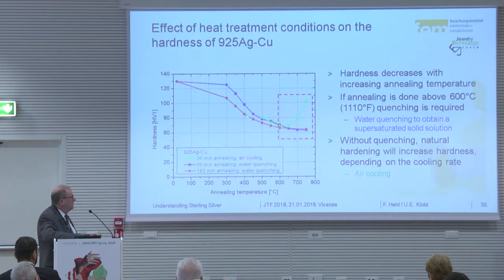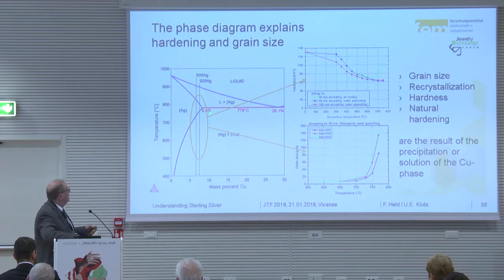If we make annealing and take it out of the oven and lay it somewhere, we see that the hardness increases again, and we get up to 100 or more than 100 Vickers. That's a self-hardening effect if we don't quench in water and use high temperature. It starts at about 600 degrees and it increases with higher temperatures. So high annealing temperature for the goldsmiths, if you don't quench in water, only makes it harder, and you get also oxidation. So that's a point we want to explain.